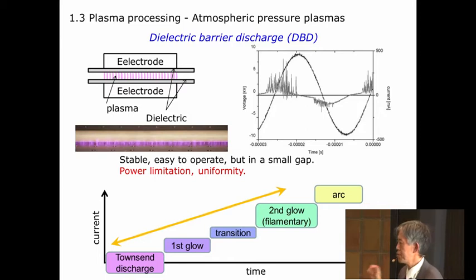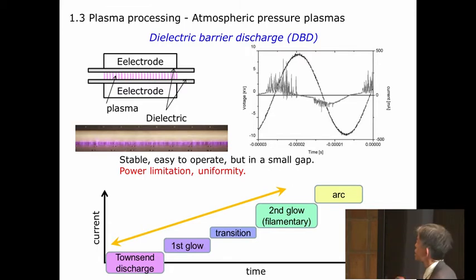And although I said it is low temperature plasma, if you want to increase the speed of the process and you increase the power, then the plasma can turn into a thermal plasma, or arc plasma can be generated. Therefore, there is a power limitation. And also, as you can see, in some conditions, plasma can be shower-like, filamentary micro-discharge is generated, and then the treated surfaces can be treated non-uniformly. So uniformity can also be a problem.